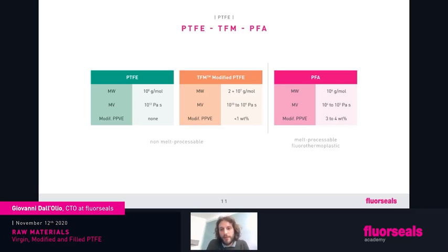Here comes PFA. PFA is, to some extent, almost the same as modified PTFE because it's a chain of PTFE. During the polymerization, the modifier will start this ramification of the chain, but we add more modifier and we have a polymer, and you can see it by number, with a lower molecular weight, with a viscosity that is lower, and so this leads the PFA to be a melt processable fluoropolymer. As you can see, just super fast, we will see the numbers.